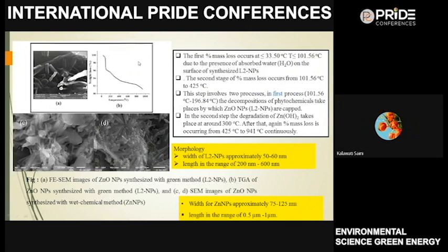When it is heated, first of all the H2O adsorbed on its surface is evaporated, and the second mass loss is from 101.56 degrees centigrade to 425 degrees centigrade. In this there is this one, this one, and then this one. There are two mass losses. These mass losses in this area are due to decomposition of the phytochemicals present in the coating of the zinc oxide particle.